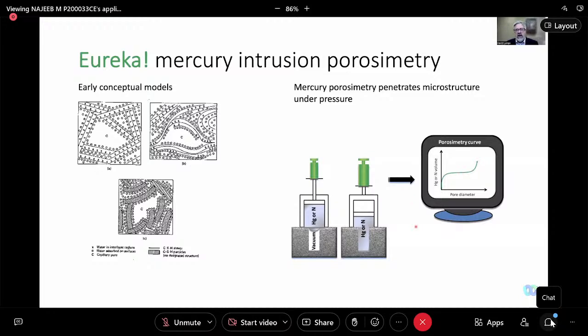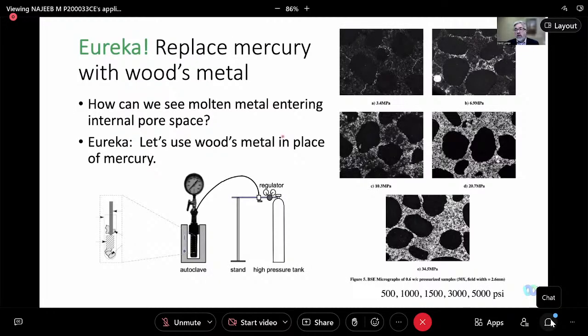And so this was somewhat of a non-contact, a blind way to measure microstructure, measure pore structure. But for a while, it was the best thing going. And we wanted to look at that a little bit more closely. And we thought about, well, let's do it differently, because we really need to inspect these microstructures. Let's replace that mercury with Woods metal. Woods metal is a metal that melts at about the temperature of a cup of coffee, odd cup of coffee. And so we could do that safely. And then we could press that, apply pressure, and push that into the microstructure, and then hold that pressure while we reduce the temperature to allow the metal to solidify. And by doing that, we could get these step pictures.